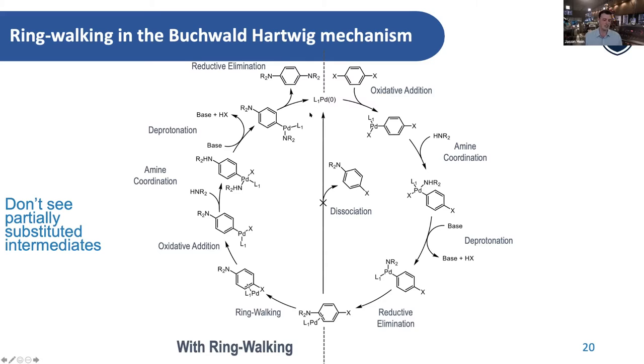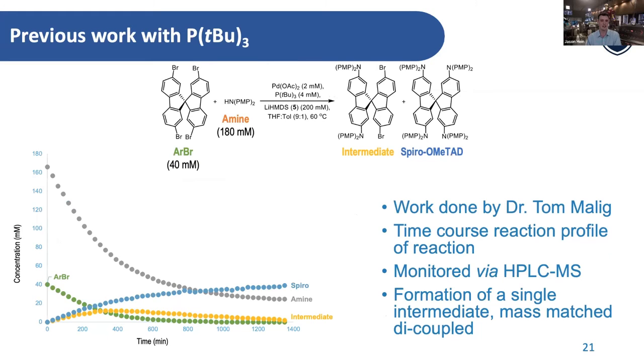So what this means is, if you control this event properly, you've suddenly taken that really complex situation, well, I've got four different halogens to work through, and you've actually reduced it. In fact, I just need to do, along the same contiguous pi system, two CN cross-couplings, which will happen together, followed by two additional ones. So by leveraging ring walking, you could start to reduce the number of ugly possibilities if this was something you could take advantage of. And in fact, what we found is this is actually possible.